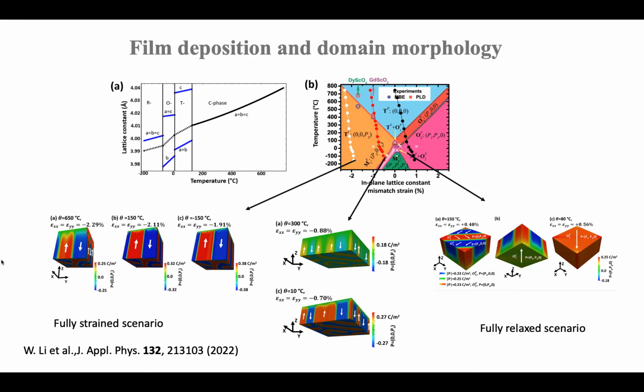Essentially what we did, so this is the famous diagram, right? Where they show the whole phase diagram of barium titanate as a function of temperature and strain. Negative here is compressive, and this is tensile. Here you see it's orthorhombic of various kinds. There's a monoclinic phase, here's tetragonal, and so how do you know where you are? Well, you don't. And so we make guesses. Essentially we said there are two limiting cases. One is you're fully strained, and the other one is you're fully relaxed at high temperature. And then you know what each lattice constant is doing, so you can go and run the simulation and follow a particular scenario.